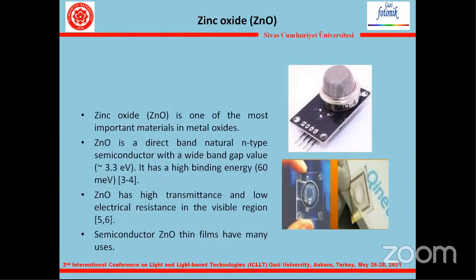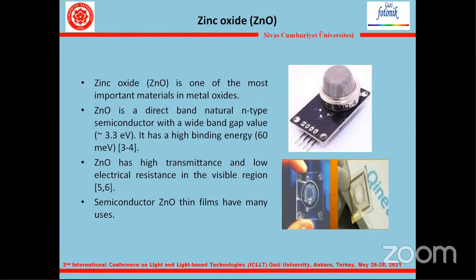Why did we choose zinc oxide? Zinc oxide is one of the most important materials among metal oxides. It is a direct band gap, natural N-type semiconductor with a wide band gap value of approximately 3.3 electronvolts. It has a high exciton binding energy of 60 millielectronvolts. Zinc oxide has high transmittance and low electrical resistance in the visible region. Semiconductor zinc oxide thin films have many uses such as gas sensors, organic wastewater treatment, layers of photovoltaic cells, photodetectors, various electronic and optoelectronic devices, and biosensors.